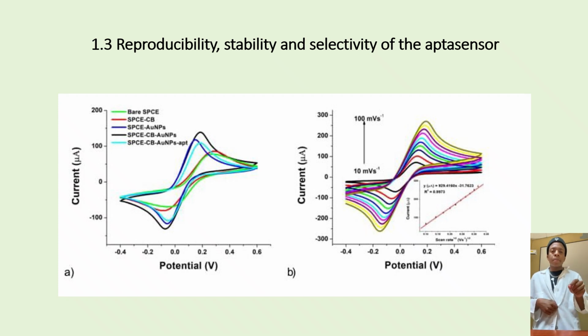We then modified the SPCE with both gold nanoparticles and carbon black, and added an aptamer. This resulted in a lesser reading than we expected, again due to the repulsive forces between the aptamer and the probe.